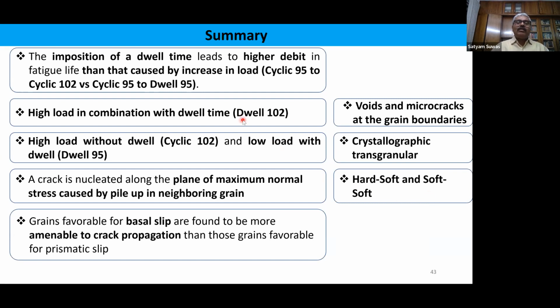And then higher load in combination with dwell time leads to voids and microcracks at the grain boundaries. Higher loads without dwell, and low load with dwell, lead to crystallographic and transgranular cracks, which we have just seen. And a crack is nucleated along the plane of maximum normal stress caused by pileup in the neighboring grain, that is the hard-soft and soft-soft combination. And grains favorable for basal slip are found to be more amenable to crack propagation than those grains favorable for prismatic slip.